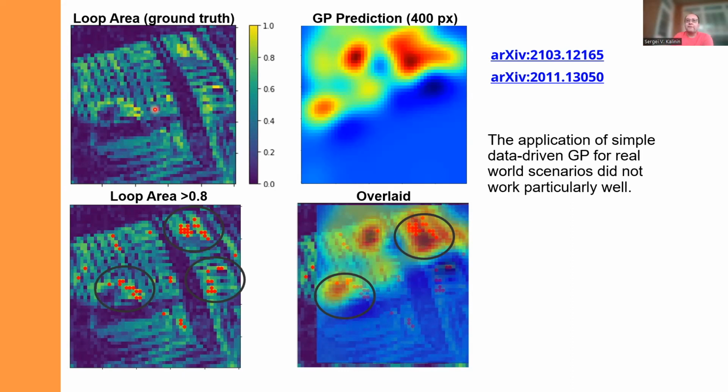So practically, after spending quite a lot of time experimenting with Gaussian process workflows, both for electron microscopy data, sort of STEM, structural, EELS, and SPM data, it seems that in the general case, Gaussian process can give us an advantage of 2 to 3 in terms of the number of scanning points.